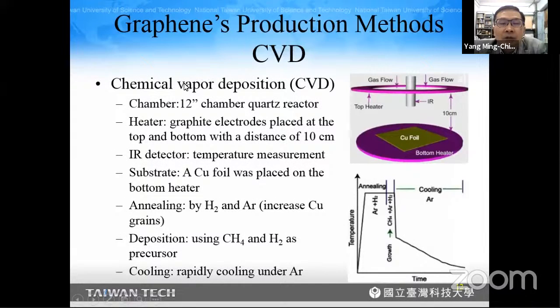Now, first, about the details of chemical vapor deposition. Basically, the reaction takes place in a chamber, usually a 12-inch chamber of a quartz reactor. This is a heater. Graphite electrodes are placed at the top and bottom with a distance of 10 centimeters. And there's an IR detector for measuring temperature. And the substrate is a copper foil at the bottom of the heater. It is annealed after heating, annealed by hydrogen and argon to increase the copper grain size.